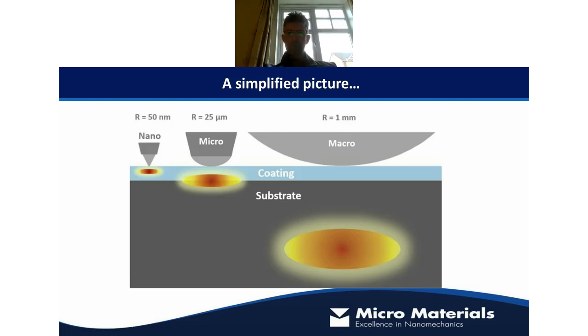So, a very, very simplified picture now of the depth of the peak stresses for plasticity, for example, in a coating system. What we can see is as we change the probe radius, we change the depth at which those peak stresses are developed. And if your mechanism involves substrate yield through plasticity, then the results you get are going to be very, very dependent on where those peak stresses are. Obviously, it's more complicated in the sliding contact system, and I'll show you where we can model this and get more accurate data.